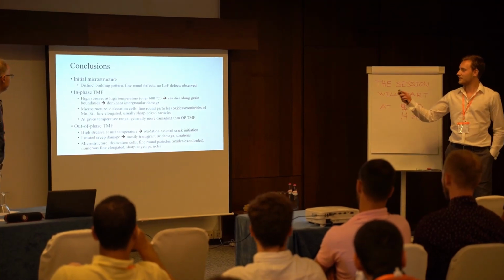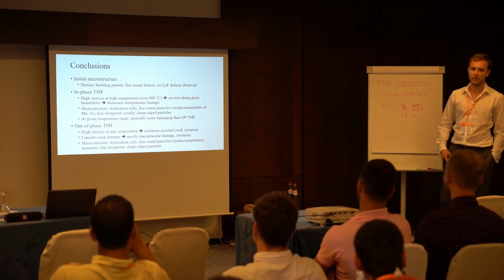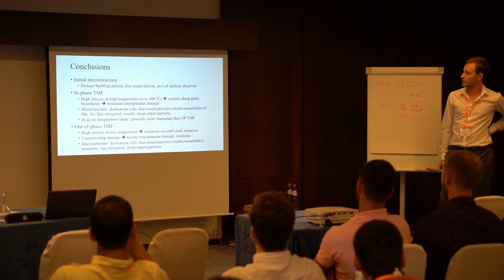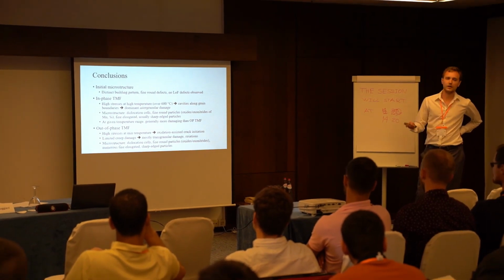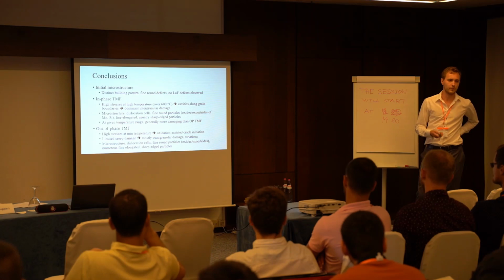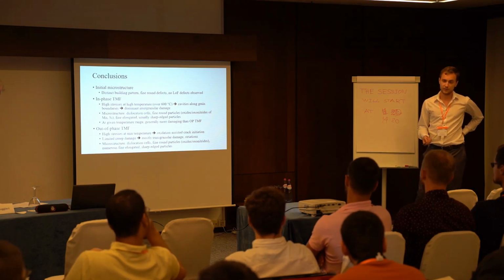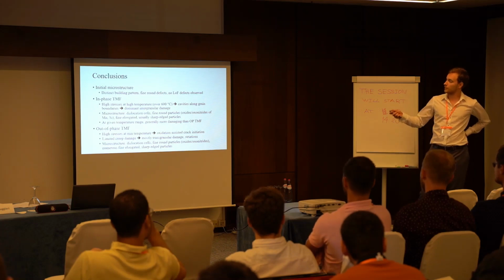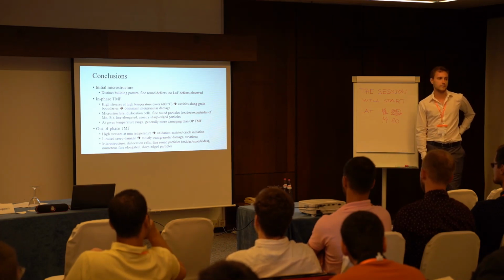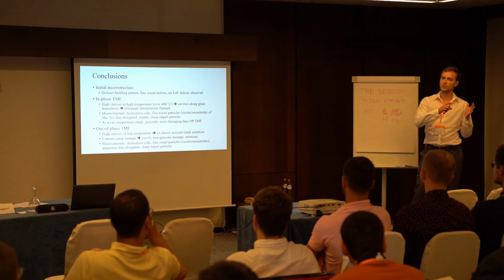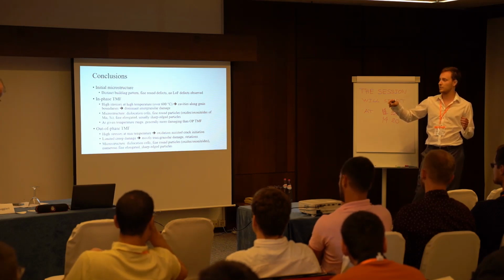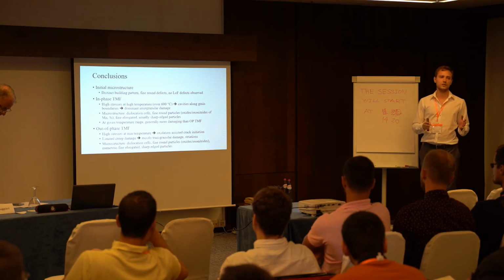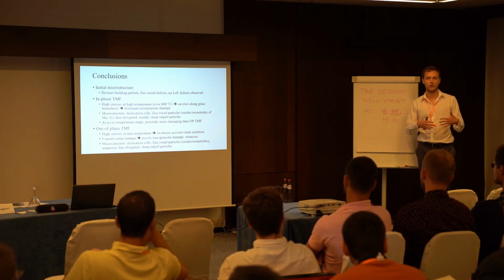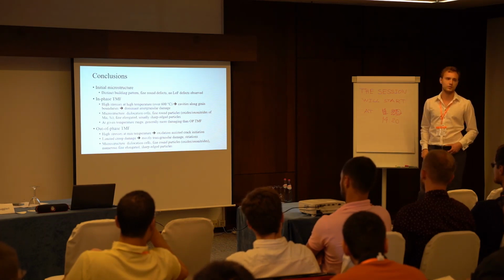Okay, to conclude my talk, the initial microstructure showed strong texture, which was related to the building process of the material. There were fine round defects present in the microstructure. Importantly, no lack of fusion defects were observed. In case of out-of-phase thermomechanical fatigue, the sequence was like this: the high stresses, which coincide with high temperatures exceeding 600 degrees centigrade, which is important for onset of creep damage in this material, led to nucleation of cavities along grain boundaries, which later grew and coalesced, and as a result we had dominant intergranular damage with massive internal damage.